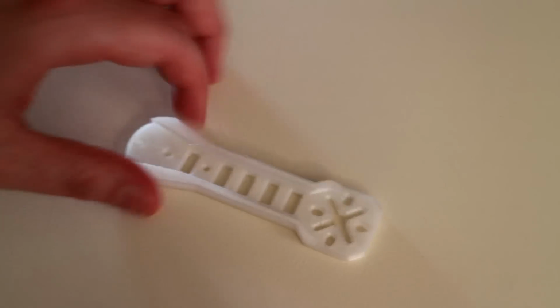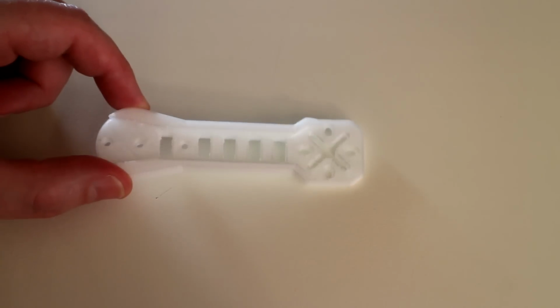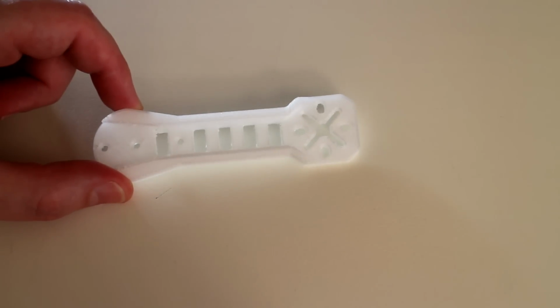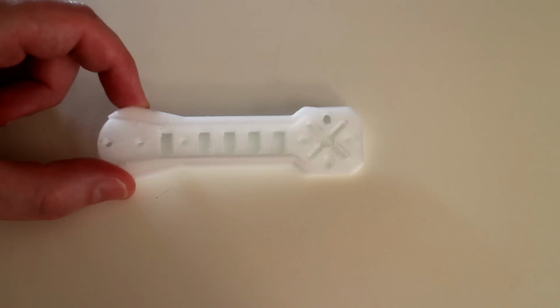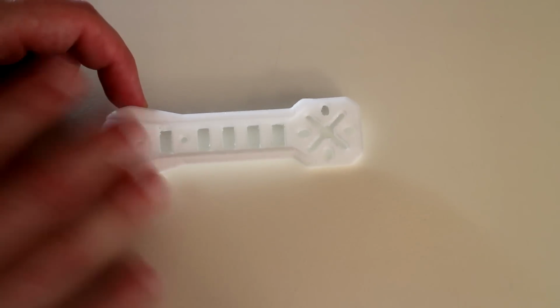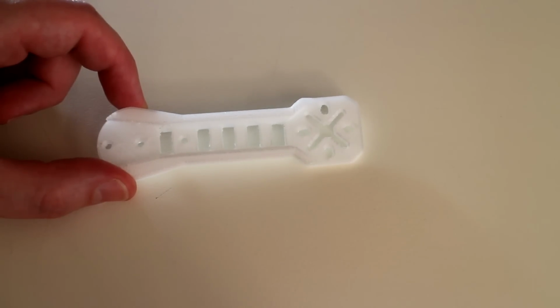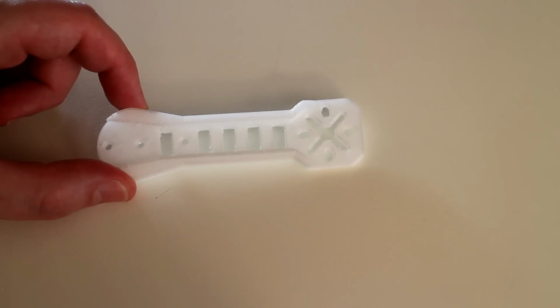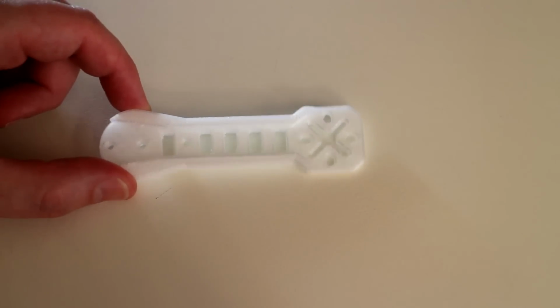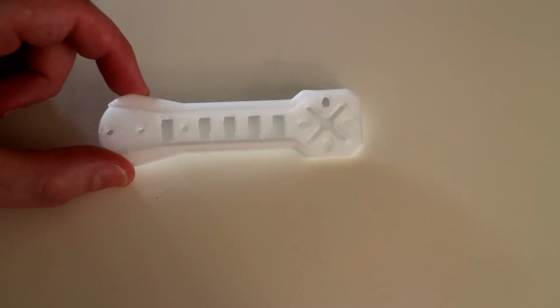And lastly, something minor, I noticed there was quite a bit of hissing and popping while this filament was printing. So the sample that I had must have absorbed quite a bit of moisture when it was sitting around, so I guess this nylon material is susceptible to moisture ingress more so than other materials.